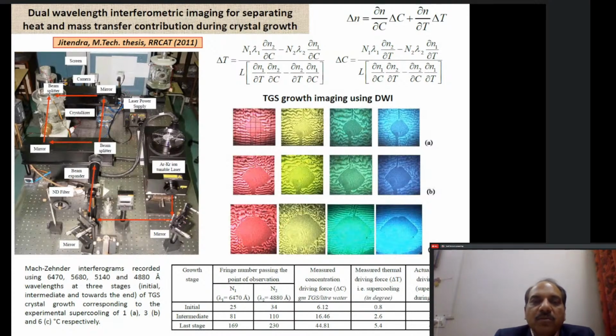But we thought that we should be able to use some technique so that we can delineate the temperature effect from the concentration effect. So we used a technique which we refer to as dual wavelength or multiple wavelength interferometric imaging. In this, we record the growth process online and in situ at different wavelengths. One wavelength is sensitive to temperature changes, and another wavelength is sensitive to concentration changes. Using these two wavelengths, in this experiment done for triglycine sulfate, we were able to find out the measured thermal driving force and the actual thermal driving force. We were able to show the contribution from thermal effects and the contribution from the concentration effects.